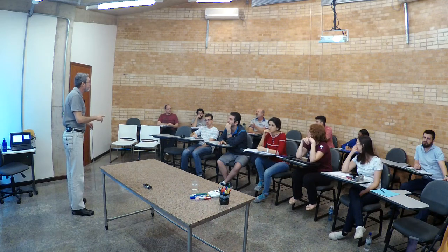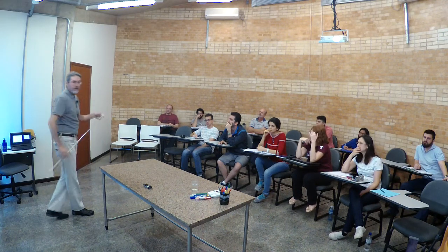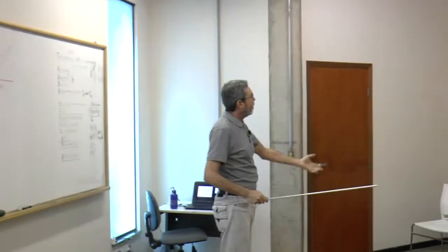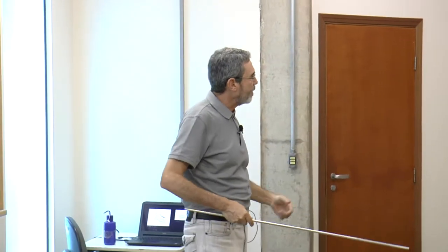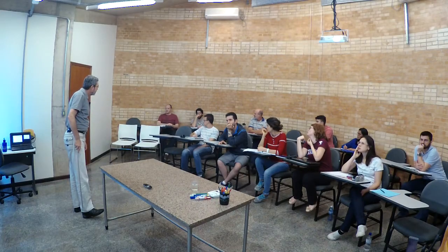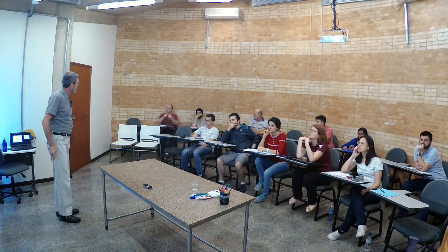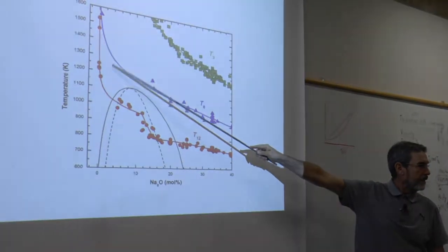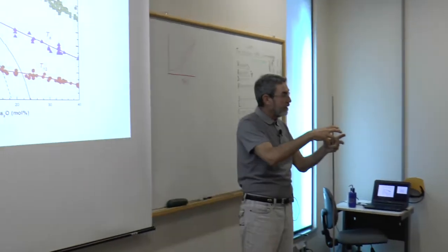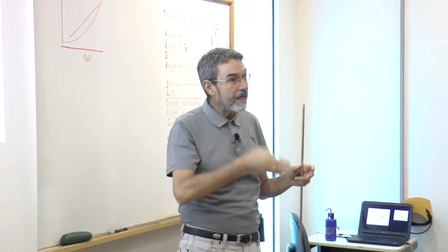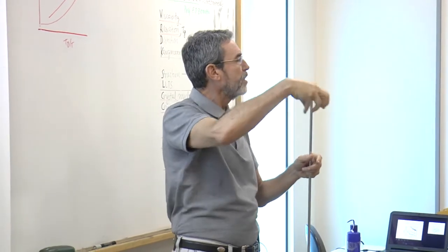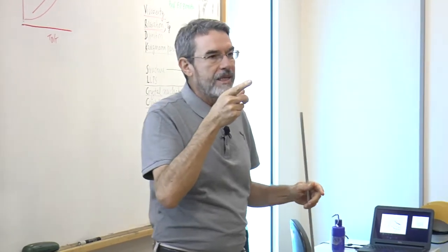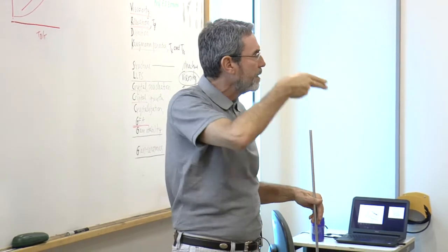Because of breaking of the linkage of silica. Yeah, but here I'm breaking also. Every atom that you add, I'm producing non-bridging oxygens. What's your idea, Benjamin? You said you had a traffic jam, like all these whatever is diffusing in the melt is competing with one another, so you can't go any faster than the next car. Yeah, here I had a traffic jam. I had that three-dimensional structure. For pure silica, all four corners are shared with other tetrahedra. Now, when I add sodium, each sodium atom breaks one bond. So you have a huge effect.